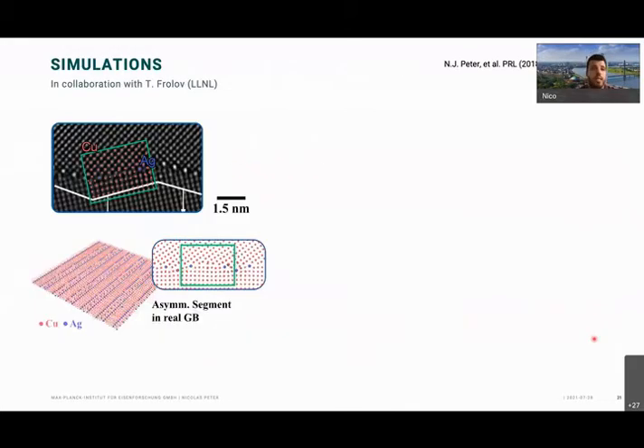We also looked at the asymmetric part, and here it's a little bit different. The asymmetric part can take up silver, however, it does it in a very linear way. So there are very long lines at certain positions along the boundary, and we chose a boundary very close to what we have, of course. And in between, there are usually gaps where no silver likes to go. And apparently, our asymmetric segments here make pretty much exactly that.